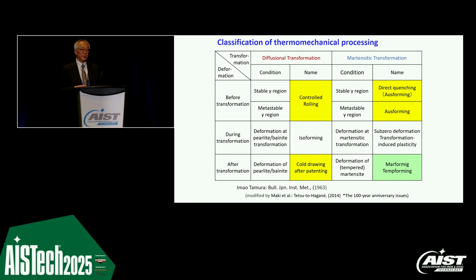So this is the classification of thermomechanical processing. Of course, we apply deformation. When we deform the materials, we separate the processing into before transformation, during transformation, and after transformation. The targets of the phase transformation are diffusional transformations, ferrite and pearlite, or martensitic transformations. The famous one, of course, is controlled rolling. We know now TMCP combined with accelerated cooling. And for applying deformation before the martensite transformation, we call that direct quenching or ausforming. And during transformations, of course, there are...